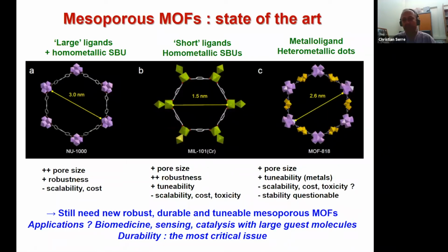So if you look at the state of the art of mesoporous MOF, this is a schematic representation of the main strategies that have been reported so far. There are basically three main routes. The first one on the left here is to use large ligands and oxo cluster. So this large ligand here is a highly aromatic tetracarboxylate ligand, and you have a zirconium-6 oxo cluster. And then as the ligand is very large and the connectivity of the building unit not too high, you form mesopores of a few nanometers.